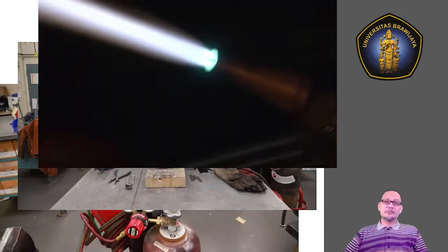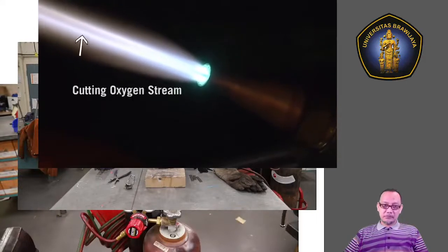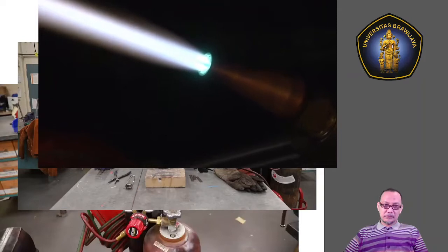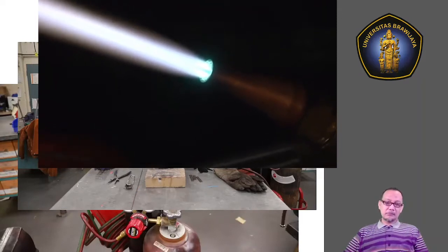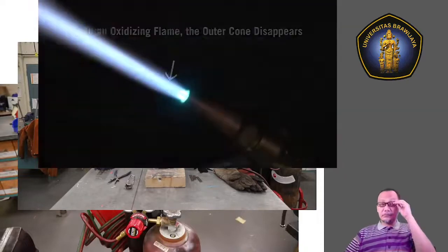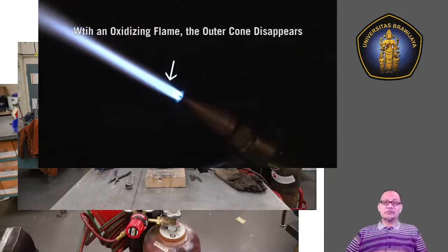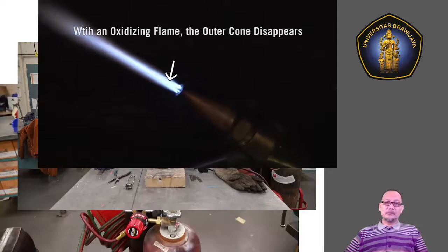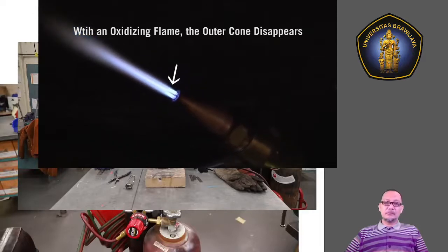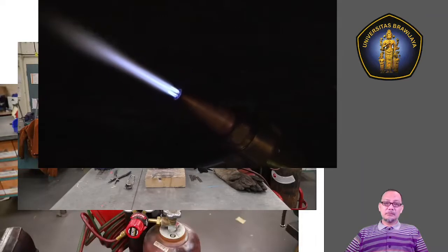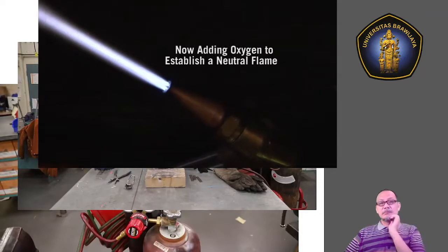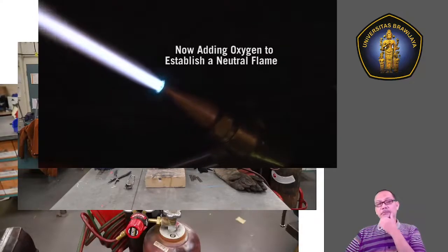At this point, depress and release the cutting oxygen lever. You may need to readjust the flame at this point. Typically, the flame becomes slightly carburizing and you'll need to add more oxygen. However, note that if you add too much oxygen, the outer cones disappear and the inner cones become pencil sharp and a loud hissing sound occurs. If this occurs, decrease oxygen flow.